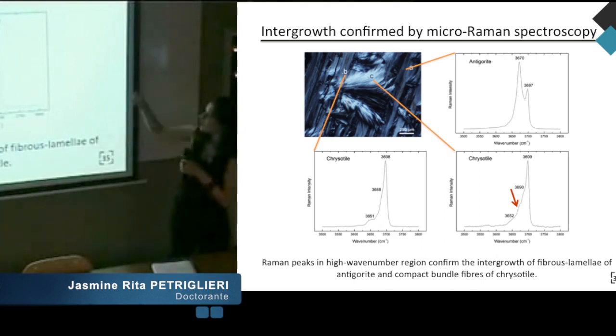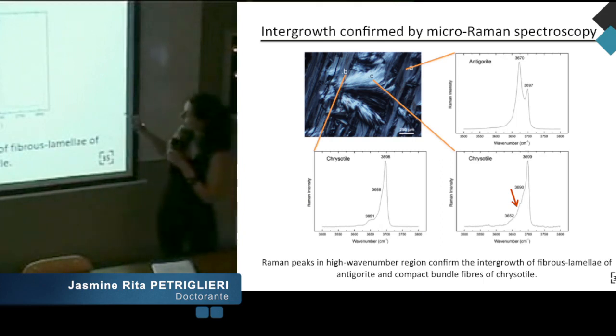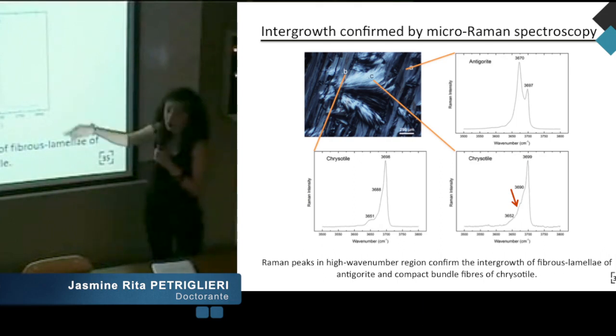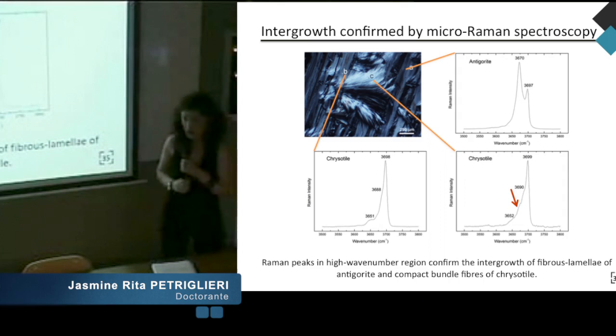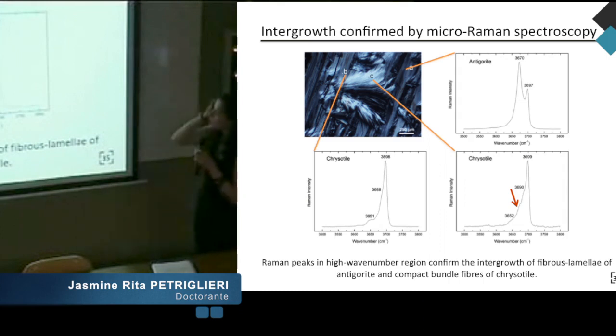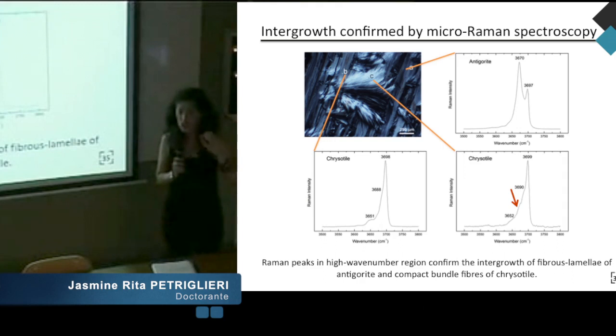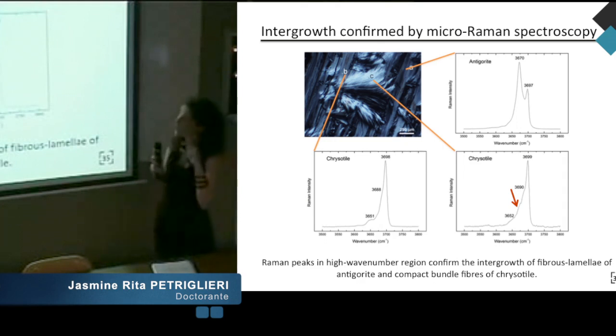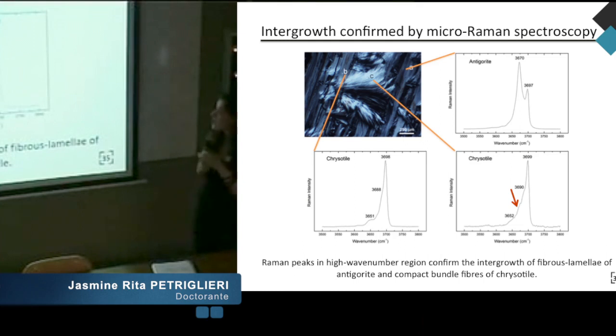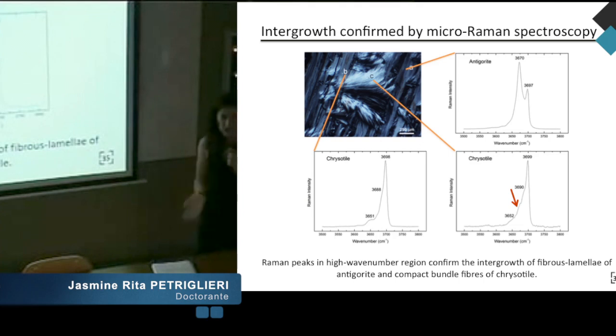The tuft — the flexible tuft — was confirmed as chrysotile. But it is interesting to note that a little shoulder, indicated by the arrow at the peak position of antigorite, is related to the thickness of the chrysotile bundles. Comparing the thickness of the tuft to the preparation of samples, the laser beam pointing directly on chrysotile penetrates and is impacted by the presence of antigorite below.